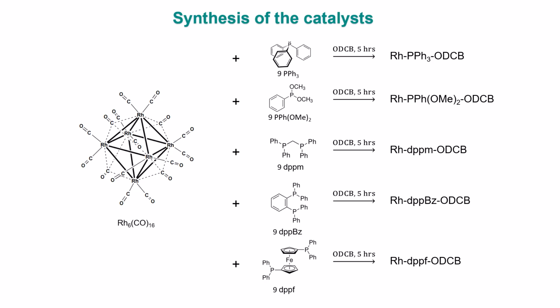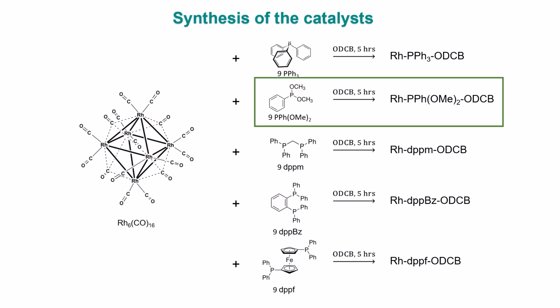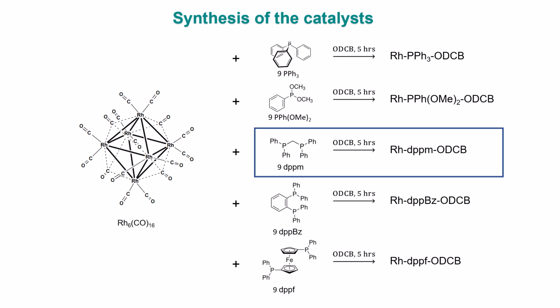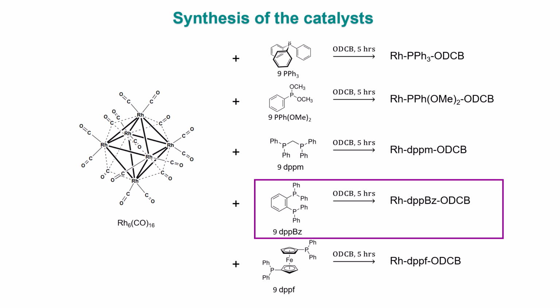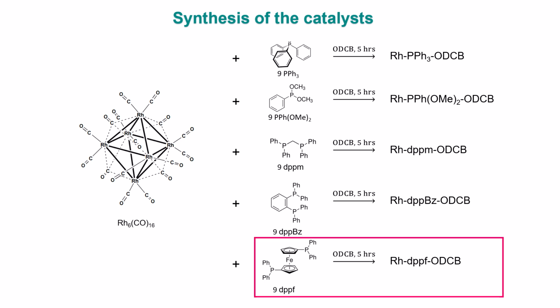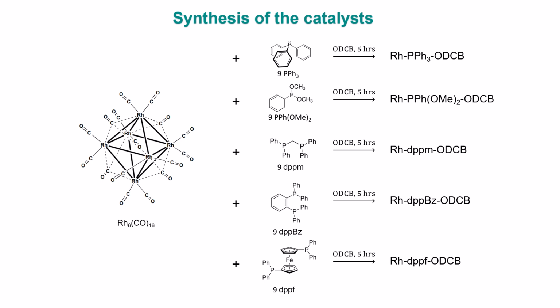Five rhodium clusters were synthesized using hexarhodium hexadecacarbonyl as the precursor, and five different phosphine ligands: triphenylphosphine, dimethylphenylphosphonate, bis-diphenylphosphinomethane, abbreviated as DPPM, 1,2-bis-diphenylphosphinobenzene, abbreviated as DPPBZ, and 1,1'-bis-diphenylphosphinoferrocene, abbreviated as DPPF. The reactions were carried out in orthodichlorobenzene under reflux conditions, producing the five catalysts evaluated in this work.